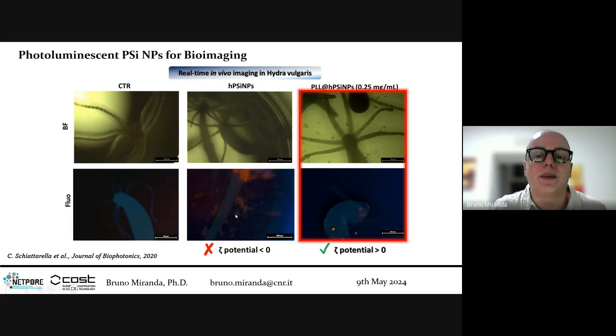What we did was testing the hydroxylated nanoparticles as they were. The animal was in good condition, but the problem was that the nanoparticles were not internalizing because of their negative charge. So we decided to modify them with polylysine, which is positive, and in this case, as you can see here initially, the nanoparticles are inside.